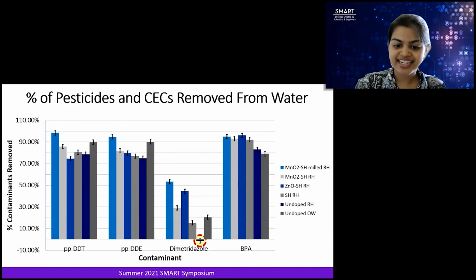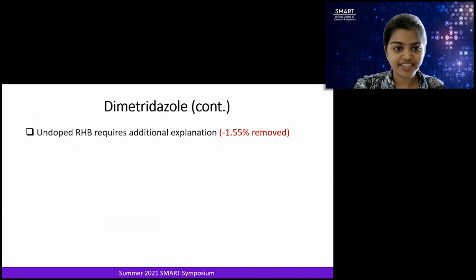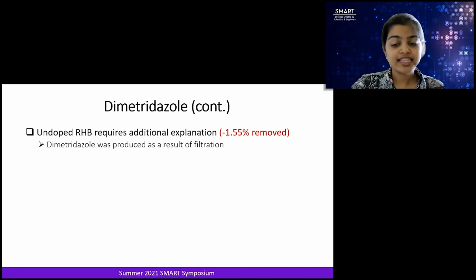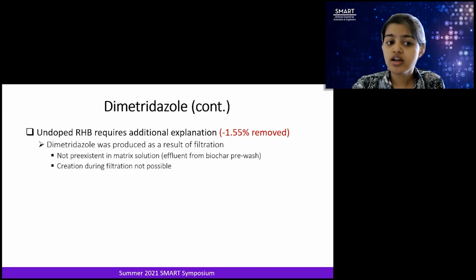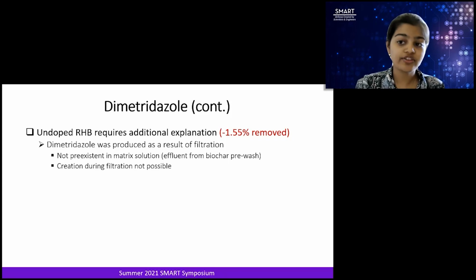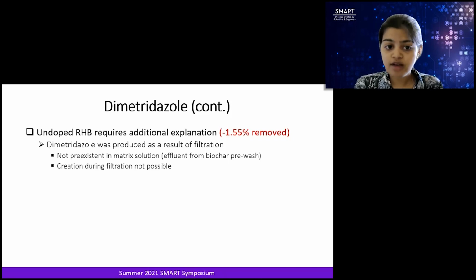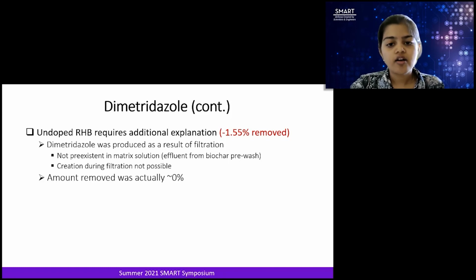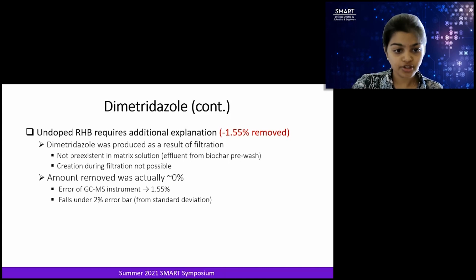Another very interesting piece of data about dimetridazole was that the percent of contaminants removed was actually negative for the undoped rice husk biochar, which requires additional explanation. Negative 1.55% was removed. This would lead us to two conclusions. Either dimetridazole was produced as a result of filtration, but this doesn't make sense for our data because it was not pre-existent in the matrix solution, which was effluent from the biochar pre-wash. So we know that dimetridazole was not produced as a result of filtration. A more plausible explanation is that the amount removed was actually 0%. Thus, the error of the GC-MS instrument is 1.55%, which falls under the 2% error bar from standard deviation.